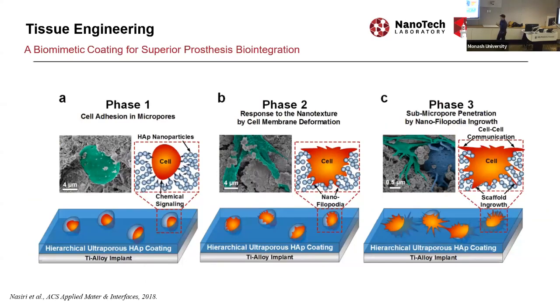Another work that we've done, again with the same coating, but this time we changed the coating from, let's say, zinc oxide or titanium oxide to hydroxyapatite. And then we create the hydroxyapatite coating on top of the implant. Because it is extremely porous, this is for cell growth.